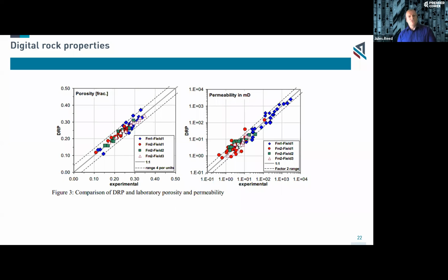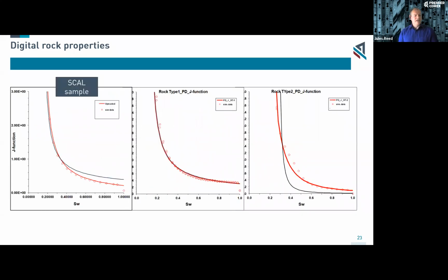But once you've tuned the model, you can then begin to do multi-phase rock properties, something like, say, a capillary pressure curve. And in this particular case, this was one sample that had, within the heterogeneity of the sample, 2 different rock types. And we're able to sub-sample the 2 different rock types, get the capillary pressure data for those, and then put those together into the larger scale sample. So those are things we can do with our legacy core.